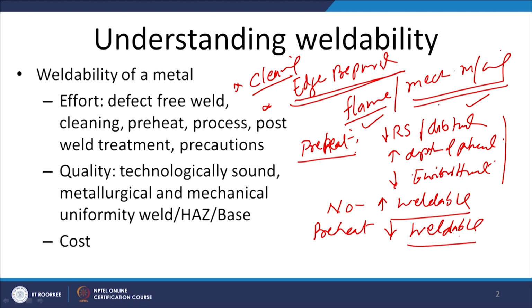Now, another thing, like if limited preheat is to be used, the preheat may vary like say 50 degrees centigrade to 300 degrees centigrade in case of the steels. So, the lower the amount of the preheat needed, the easier and better will be the weldability as compared to the cases where a higher preheating temperature is needed, because it will be more difficult to work with the preheated plates, preheated metal systems. So, the weldability will be poor. So, no preheat is the best possible situation from the weldability point of view, and if the preheat is to be used, then preheat should be as little as possible for the better weldability. The higher the preheat requirement, the lower will be the weldability of the given metal.